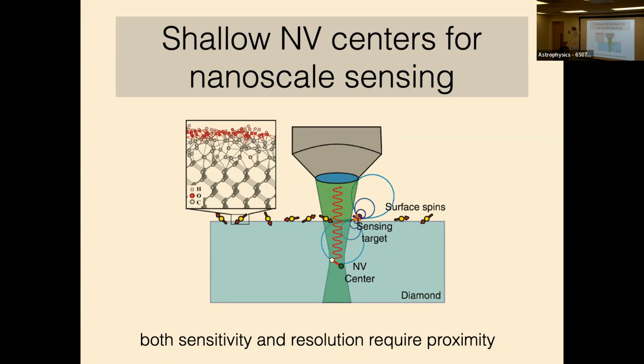Now, I need to get extremely close to this protein to get very high spatial resolution. That part is obvious, but also sensitivity is going to scale as something like distance cubed or distance to the sixth, depending on exactly what you're doing. So you really want to get extremely close to this thing. But getting really close to this thing also means that I have to get really close to the diamond surface. And while mankind is quite good at making extremely high purity diamond now, we're really bad at surfaces in general, and diamond surfaces in particular, because diamond is a very hard material. So it's hard and inert. Preparing surfaces in a way that gives you low noise is an outstanding challenge. You can think of this as the NV center is extremely sensitive, but it's going to see both the sensing target and this big background noise path.